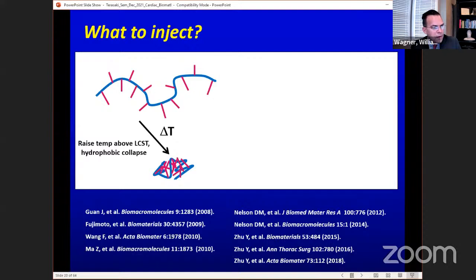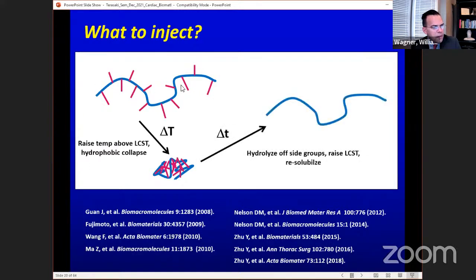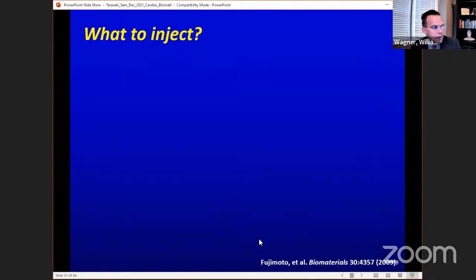And then the second part, you cleave naturally hydrolytically the hydrophobic branches, and that ends up effectively raising the lower critical solution temperature. So you're changing the temperature at which that phase change occurs, you're raising it, and it gets above body temperature and it becomes soluble again. And then it diffuses away. So we're degrading off side branches to get to the point where we can solubilize the backbone. And then the nice thing about the side branches is it allows this backbone to be lower molecular weight, so you can get it below the point at which it's going to pass through the kidneys to minimize toxicity concerns. So lots of ways to do this. I'm not going to go into all of them.